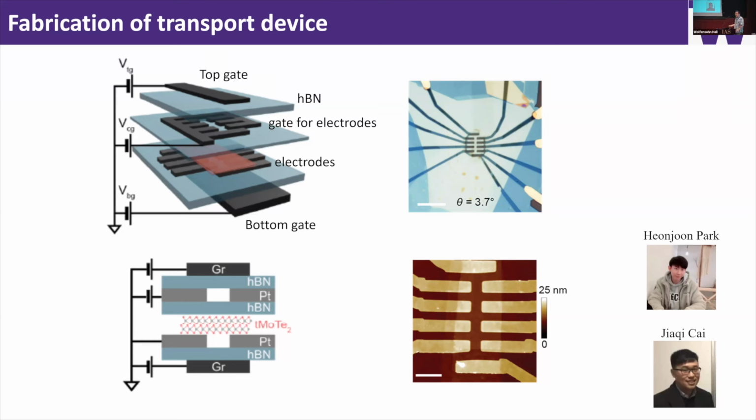One thing you will notice is that these devices are actually quite clean. We don't have any bubbles or wrinkles on the surface. For each device, we use an AFM tip to squeeze out the bubbles. My student tells me each device actually takes about 200 hours. If he's lucky. It could fail at the 199th, the last step.